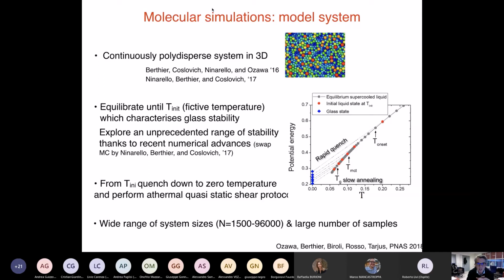And this has been done in the group of Ludovic Berthier, who used an algorithm called the swap algorithm that was invented before. But instead of changing the algorithm, he changed the system. So he found a continuously polydisperse system in which this algorithm is extremely effective. And this way he was able to equilibrate the system to a value of the temperature which is extremely small. I mean, it's comparable to the one that you have in experiments, actually even lower.